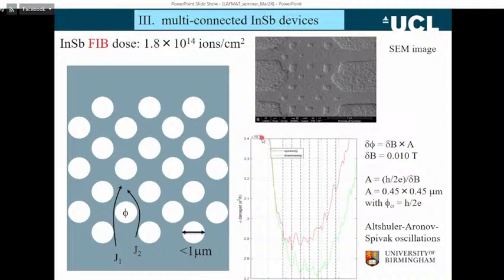Because what happens here is, as we sweep the magnetic field, the temperature changes. And if the temperature changes, you've got an exponential dependence of your conductance on temperature. So experimentally, this is a very, very difficult measurement to do. Anyway, after some persistence, we're able to see this phase coherence interaction here. As I say, the phase comes from the magnetic field and the area. If we calculate the area, this is the actual area, it's about 0.5 micron square. So each bit is 0.5 micron across. And if we calculate from the period of the oscillation, which is something like 10 millitesla, and work out what area that gives us, it gives us about 0.45 microns.